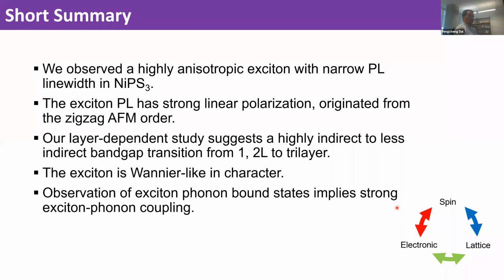So for neutron scattering, how do you determine the domain problem? How do you solve the domain problem? That's an excellent question. When you go really thin, basically there are no domains. In bulk you have domains, but when it's thin it's just naturally in one direction. If we have a layer thickness difference, then there will be domains, and we can also use this LD to actually image the domains in this structure. I didn't show you guys today, but that's an excellent question. Yeah. I'm just very curious about the nature of these excitons. I think in your result, just from the band structure, they are consistent with Wannier.